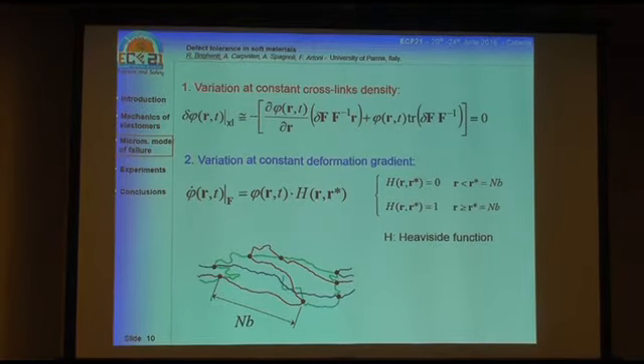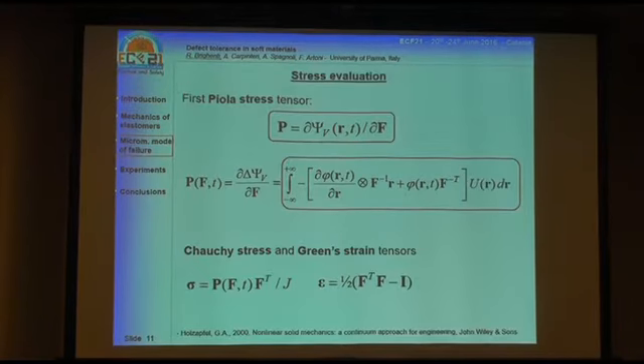So we neglect the first part, and we consider this variation, which considers that the single chain fails when we reach a maximum length, which is called r star, which is equal to nb, so n times the length of each single segment. So when the chain is straight, we can say that it can break and so it does not contribute anymore to the energy of the system.